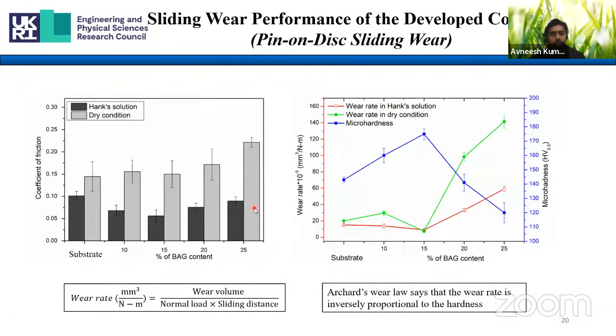Then after that, we did some tribological performance analysis using a pin on disk test. Before doing that, we did some microhardness analysis on the cross section of these coatings. From the cross-section microhardness analysis, we realized that as the baghdadite content increases, the microhardness value also increases, but there is a threshold value. After 15%, it decreases continuously.